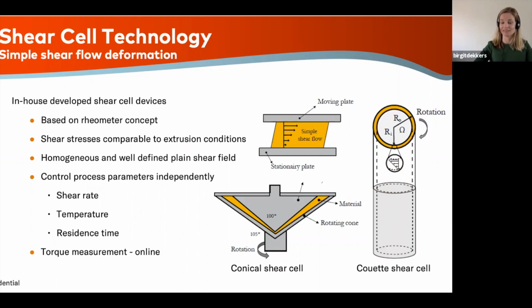So then a shear cell was designed in the group of Wageningen University, which was based on a rheometer concept, where you really have basically the idea of a stationary plate and a moving plate, where you can have simple shear flow deformation of more concentrated biopolymer systems, such that you have these shear stresses comparable to extrusion conditions. And one of the crucial things here as well is that you could heat this whole system, because most of the processes in, for example, extrusion are of course combined shear and heat, and therefore also these systems should be heated. And then the first two designs came up, a conical design where you have a cone-in-cone device where material can be placed in between, and a couette device where you have two cylinders.